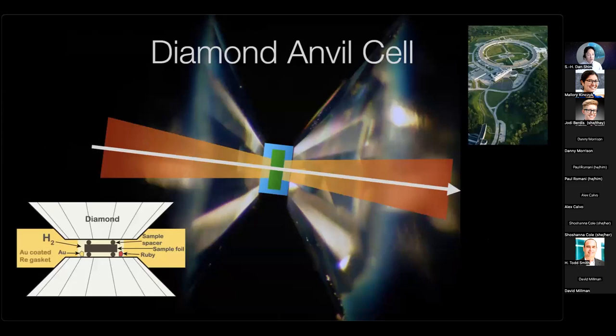The tool that I use a lot is called a diamond anvil cell, where we use two gem-quality diamonds, and then we sandwich the sample, which is represented by this green foil at the center, and then we squeeze them with the diamond anvils.